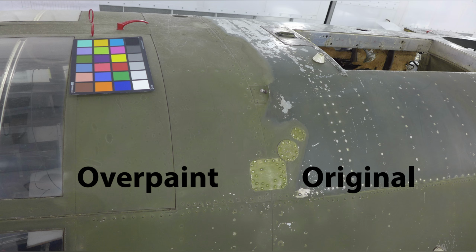When a high-velocity projectile tears through an all-metal stressed skin structure, it disrupts the continuous load path. The metal skin no longer carries tension evenly across the airframe. To prevent catastrophic failure during subsequent flights, ground crews often drilled stop holes at the ends of jagged cracks and overlaid new aluminum sheet metal. These field patches could vary from the original factory skin in thickness, fit, and finish. The uneven stiffness created localized stress concentrations around the new rivet lines.